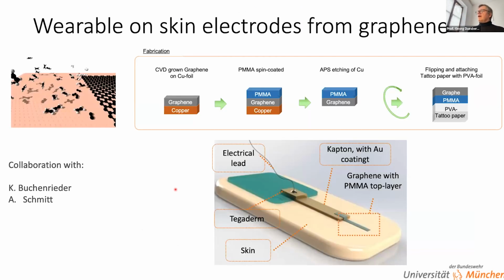If you use this, you can directly make an electrode for skin without any modification. And the integration scheme would be like this. We take the graphene on copper, coated with PMMA, as you do in each wet transfer, as a supporting layer, and then we flip the whole thing around and put it on tattoo paper with still the PMMA remaining. And then we can use this tattoo paper basically to attach it directly onto skin. Before that, we have to engineer an electric lead to it, and we use this Tegaderm, which is basically medicinal tape, to attach it to skin. But at the end of the day, we have a direct contact of this graphene layer to the skin.